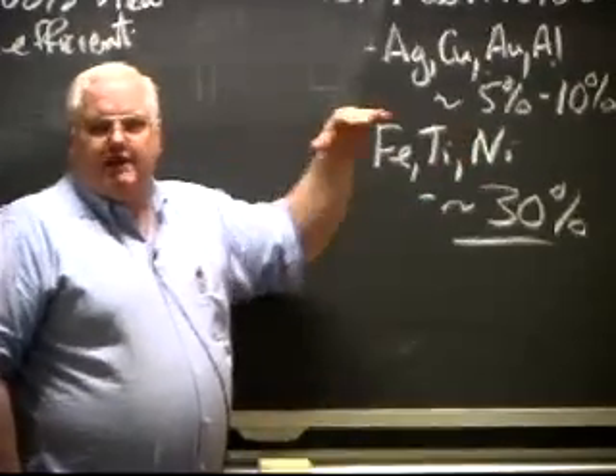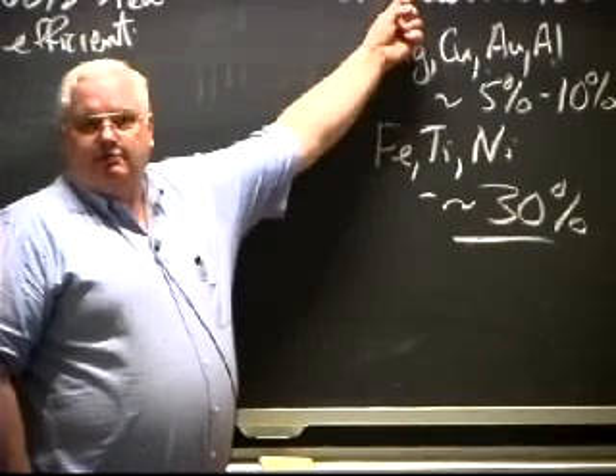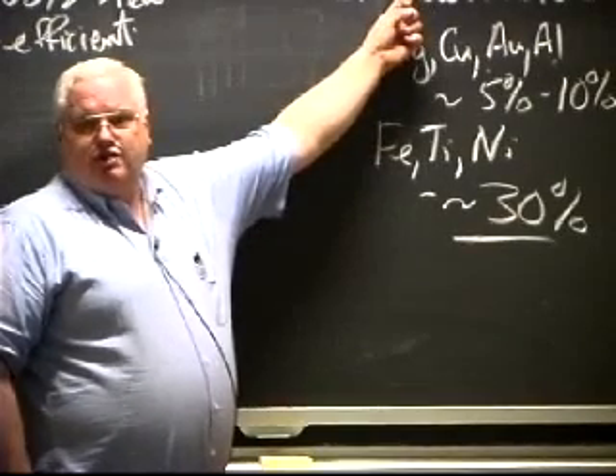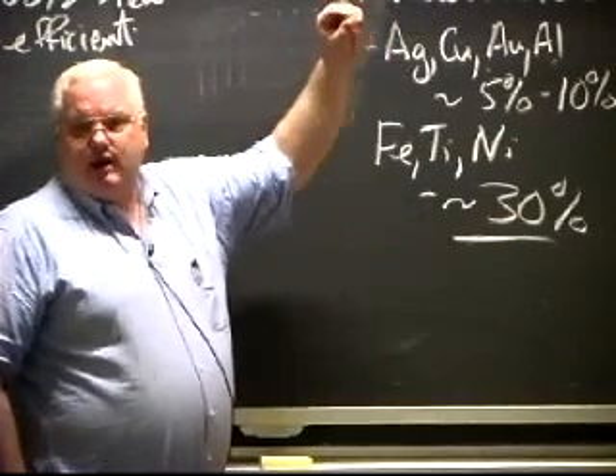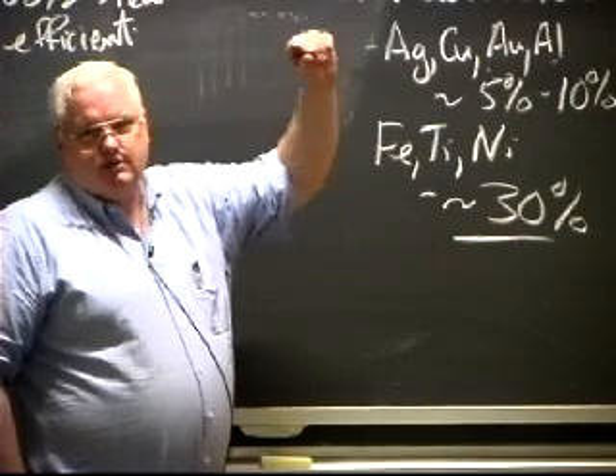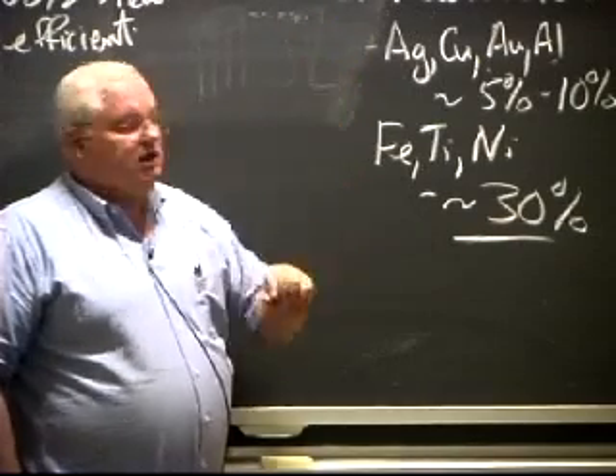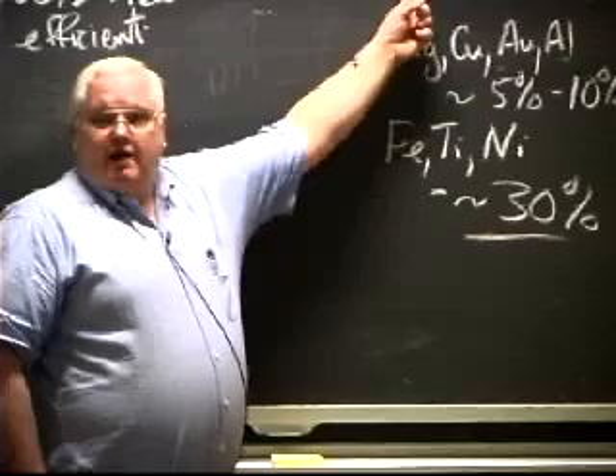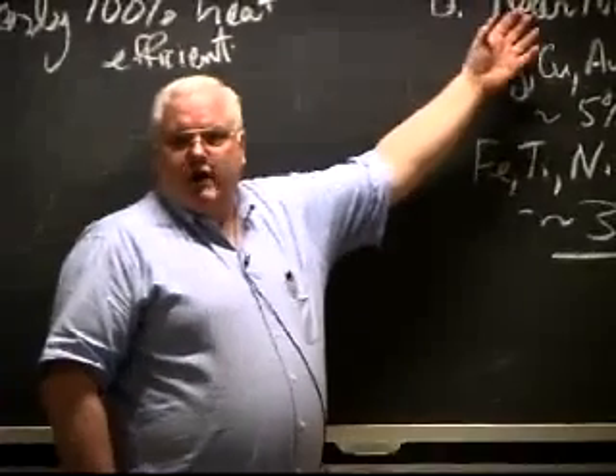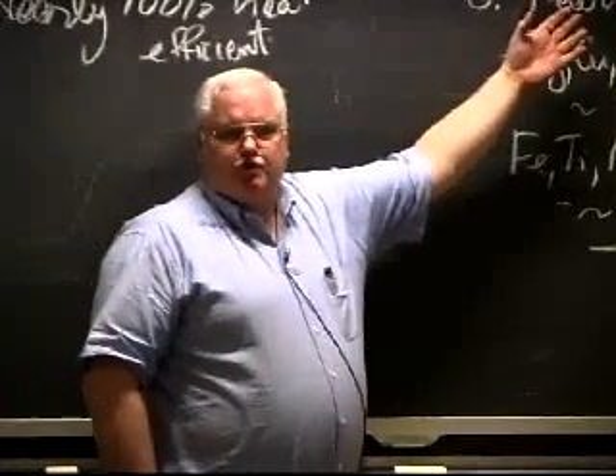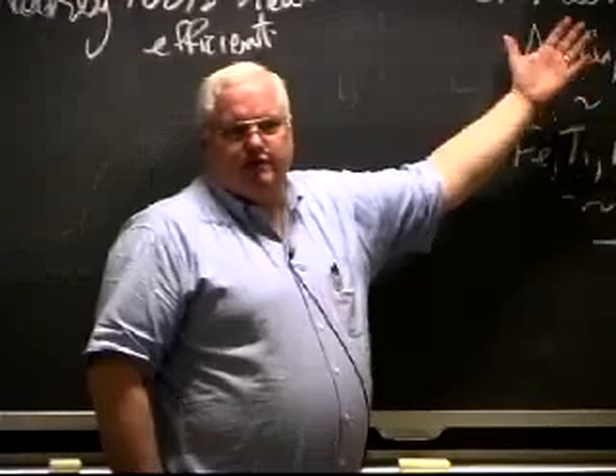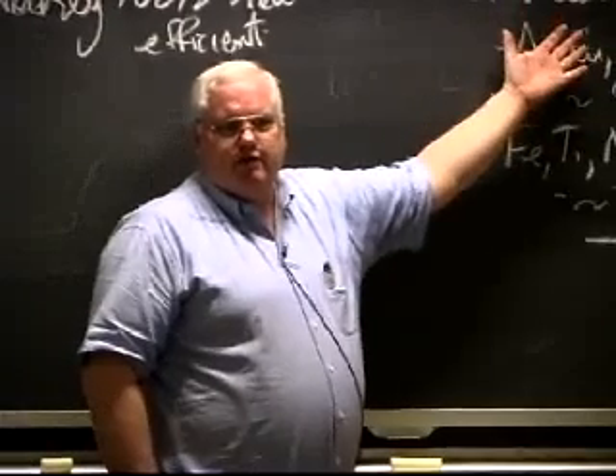But if you anodize the aluminum, now I have a ceramic, right? So the top surface is about 10 microns thick, and we actually anodized to different thicknesses. I think we did 4, 6, 8, and 10 microns. As you get closer to the CO2 wavelength, you start to get to 100% absorption. With 4 microns, we were only getting about 50% absorption because it was shorter than the wavelength of the light.